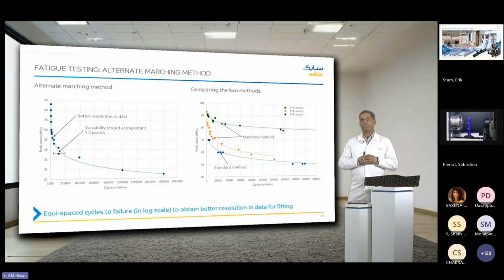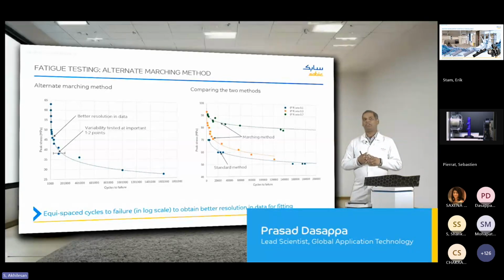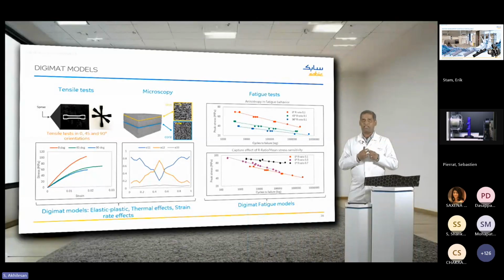Here the principle is that instead of the repeats, we perform tests at finer increments of stresses or cycles to failure. The result is, as you can see here, better resolution in the data and hence better fits to the data. Along with that, in order to obtain an idea of the variability in the data, we perform repeats at 1 or 2 stress levels. So overall, this method helps us get better resolution data and better models. Now that you have seen how to obtain the test data, let's take a look at the models.